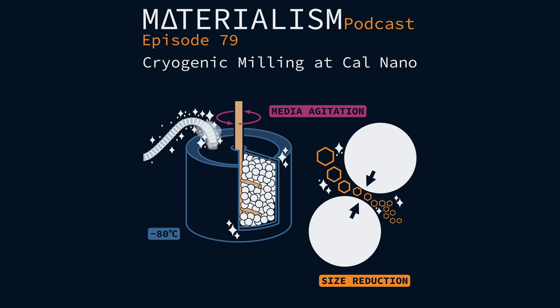Yeah, and that's what we've seen on a practical level, where we've done the pre-cryomilled material, so like a pre-alloyed, and then we've cryomilled it. And then we've seen how they sinter, and it's very visible that the cryo material actually sinters at a lower temperature and for less time. Not so surprising. It's exactly what you're saying. And that makes a big deal.